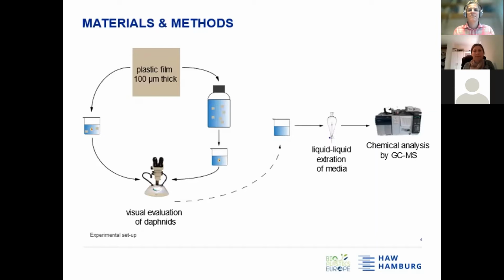The daphnids were removed from the media, and only the media was extracted by liquid extraction with hexane. This was done because we wanted to analyze the chemical pollutants which were leached out of the plastic materials. After the extraction, the extracts were analyzed chemically by GCMS, gas chromatography mass spectrometry, with regard to organic pollutants like phthalates or bisphenol A.